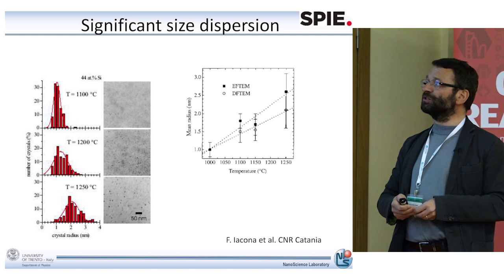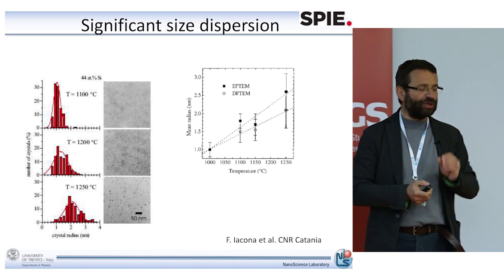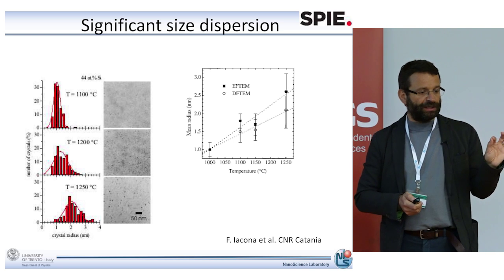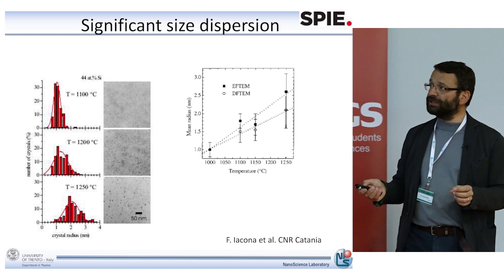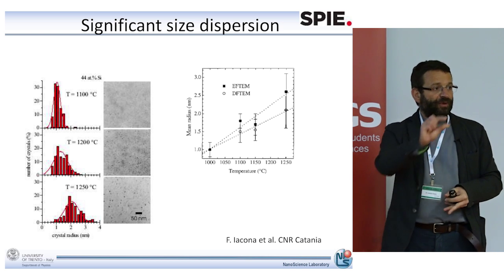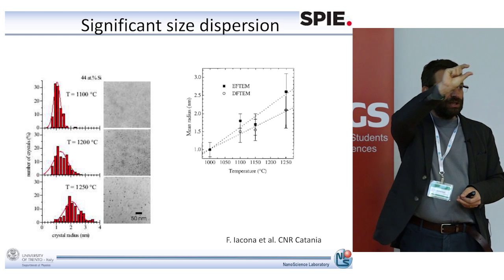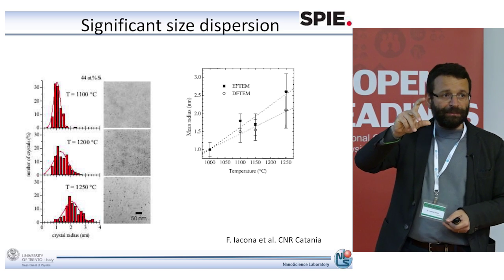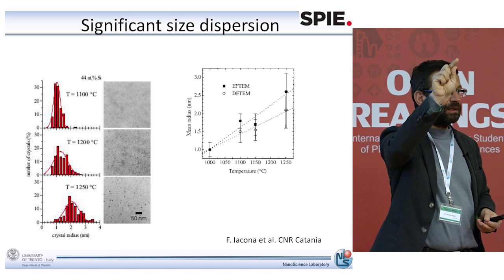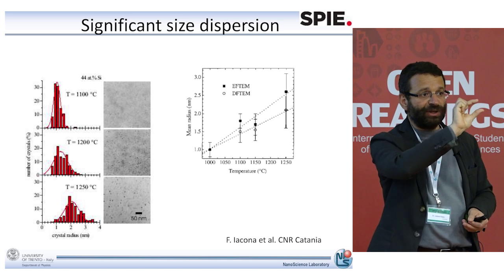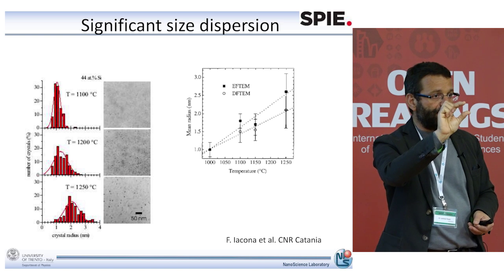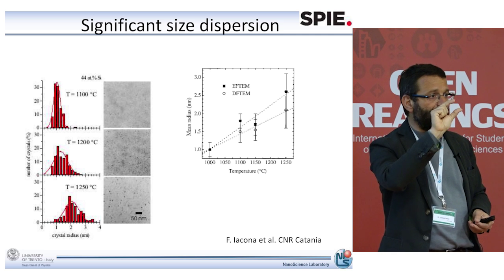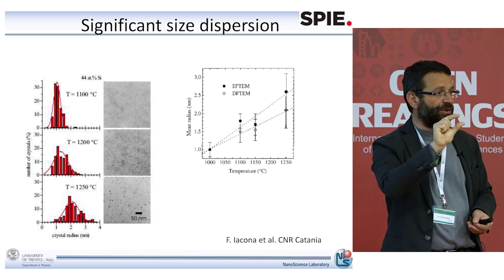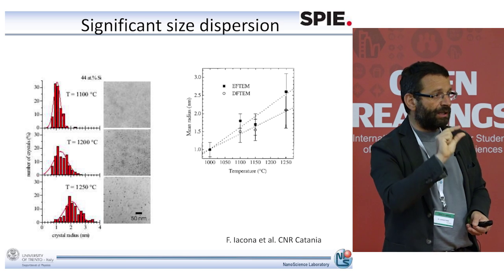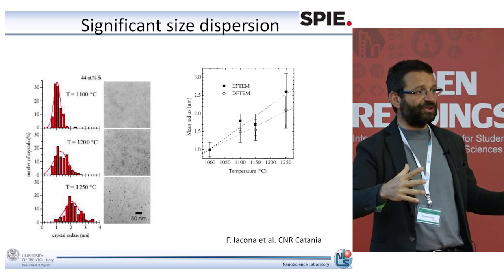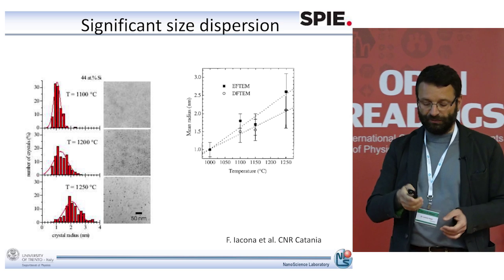However, it was demonstrated that if you constrain now the growth to a specific layer, you can control the size of the nanocrystal. So the idea is the following. You deposit a multi-layer structure of silicon-rich oxide, silicon oxide, silicon-rich oxide. And then you anneal. And it happens that the silicon do not want to enter into the silicon oxide. So the growth of the silicon nanocrystal is confined to the layer where you have deposited the silicon-rich oxide. So now the size of the nanocrystal is determined by the thickness of the silicon-rich oxide that you have deposited. And so in this way you can control the thickness and the size of your nanocrystal. And you no longer get a broad size distribution, but you get a controlled size distribution of your silicon nanocrystal.